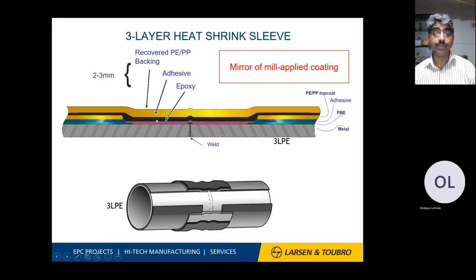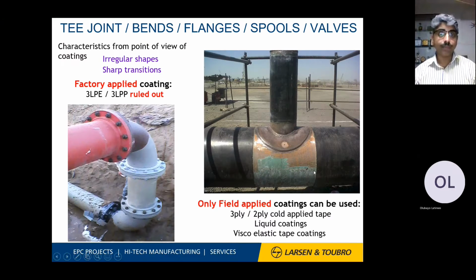Then you have to apply adhesive. Then you have to apply polyethylene and polypropylene backing. This is in the range of 2 to 3 mm. So it's a very high quality coating which we can have for any site application requirements. This process itself is called heat shrink sleeve. Compared to normal epoxy coating applications, this is a costly one.